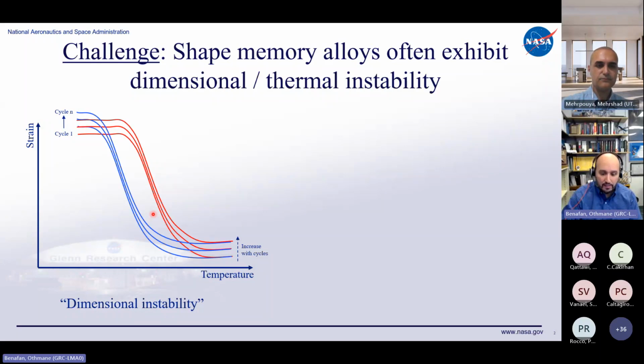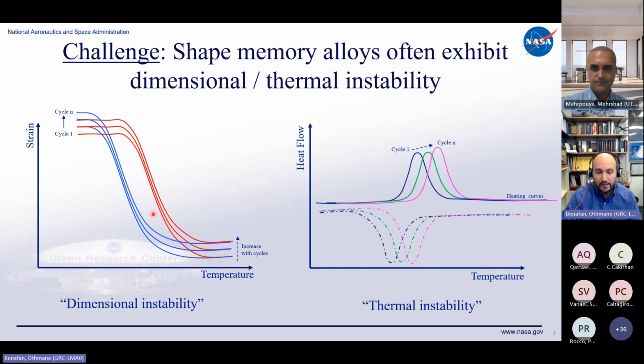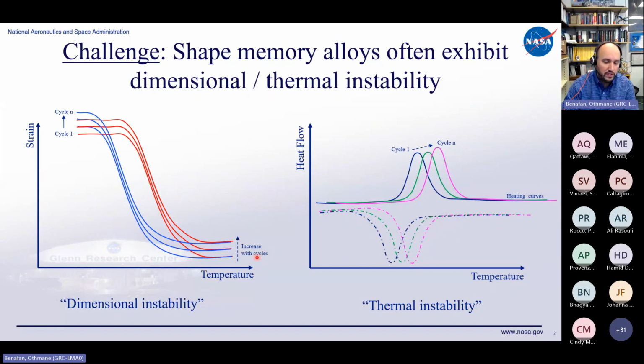There is another type of instability, which is thermal instability. This is something that you get from a DSC, differential scanning calorimetry, for instance. This cartoon shows that when you cycle from cycle 1 to cycle n, the thermal peaks not only shift one way or the other, but can also shift on the enthalpy side of things. So these are the two things that most SMAs encounter before doing some sort of strengthening. So how do you strengthen shape memory alloys against these two? This has implications for fatigue, durability, and all sorts of things.